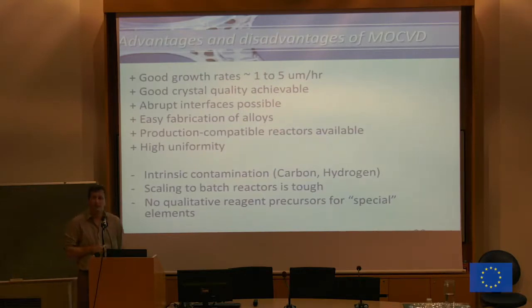However, practically in production, everybody is using MOCVD because it has a number of very clear advantages. The growth rates are reasonable, crystal quality is quite okay. Important is we can make atomically abrupt interfaces. And as we're going to do heterostructures, it is of course crucial that these interfaces are sharp. Alloying is very easy, and you can even do production-like reactors that give you reasonable yield. So in that sense, it is quite an interesting technology.